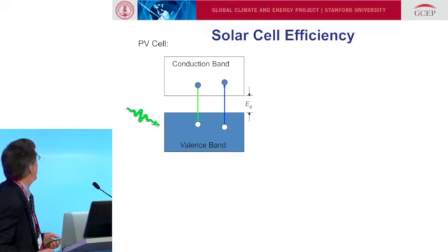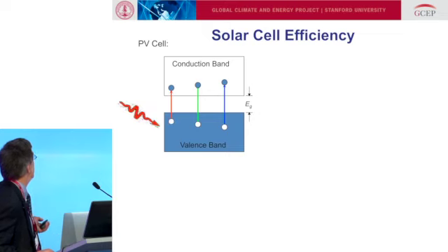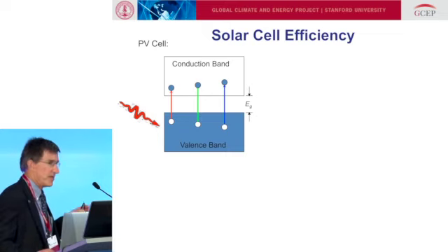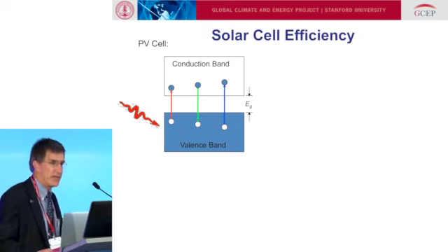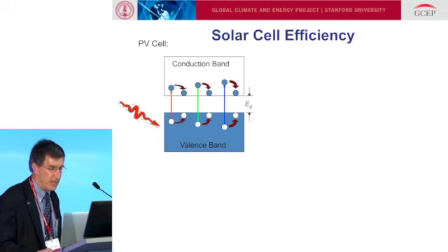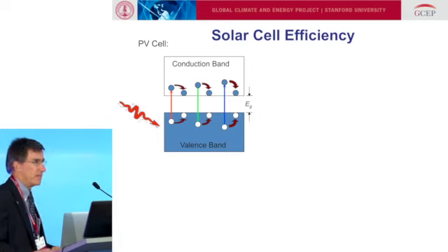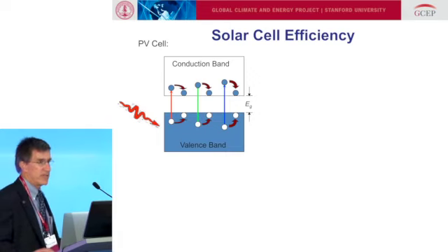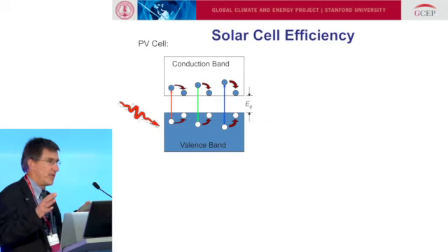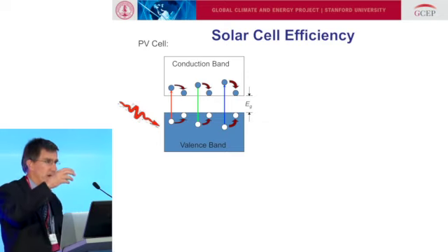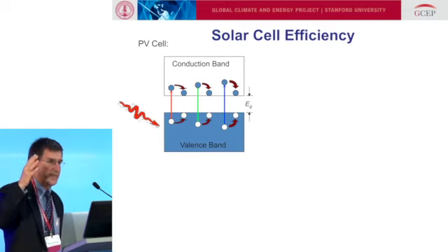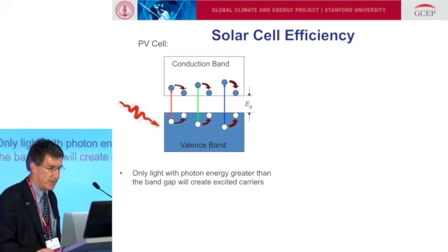So you can hit it with higher energy light, and you get a big excitation from deep in the valence band to high in the conduction band, and with lower energy light you get less, and with even lower energy light, they're even closer to the band edges. If you get low enough energy light, you don't have enough energy to kick the electron from the valence to the conduction band. But what happens immediately is you lose that extra energy, because the hole relaxes up towards the top of the valence band and the electron relaxes down towards the bottom of the conduction band. So any extra energy that photon had above the band gap energy, you lose with a single junction solar cell.